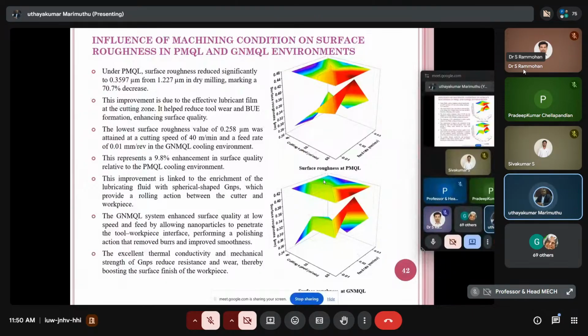Right. The improvement is linked to the enrichment of the lubricating fluid with the spherical shape GNPs, which provide a rolling action between the cutter and workpiece. The GNMQL system enhances surface quality at low speed and feed by allowing nanoparticles to penetrate the tool-workpiece interface. And in that way, we claim that the superior surface finish is realized by adding this environment, the GNMQL environment.